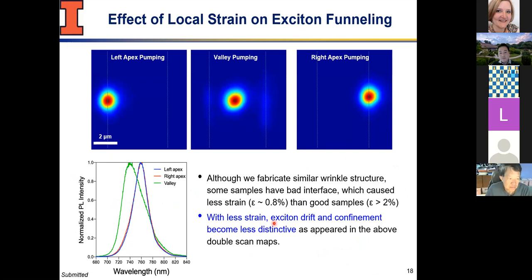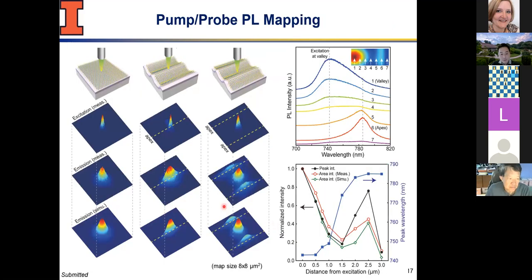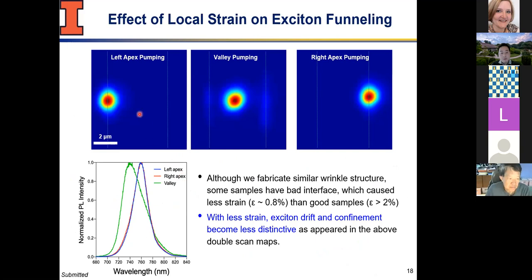But what if the strain was very little? This is our one control experiment, where if I go back one slide, if I pump the apex or the valley, you see satellite peaks or anisotropic emission. But when you do the same thing, pumping the apex or the valley or the other apex, the emission is circular, or you don't quite see that, when the strain is relatively small. In this case, it's about 0.8% versus the sample that we've been making, which is about 2%.